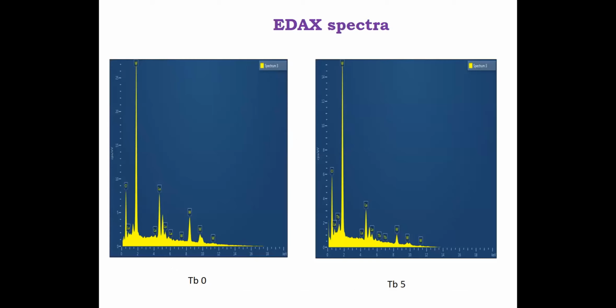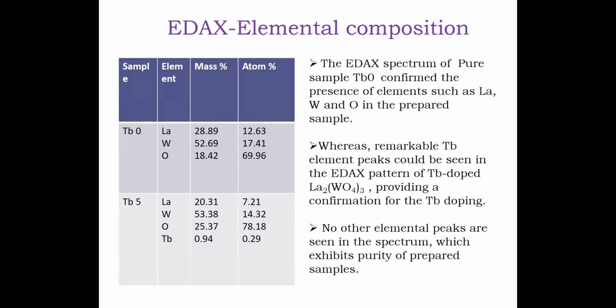Then these are the EDAX spectra of the prepared samples. It reveals the elemental composition of the synthesized samples TB0 and TB5. The EDAX spectrum of TB0 confirms the presence of lanthanum, tungsten, and oxygen. Next slide, please. No other elemental peaks are seen in the spectrum, which indicates the purity of the prepared sample, whereas the peaks of terbium ions could be seen in the EDAX spectrum of the doped sample, providing a confirmation for the terbium doping.